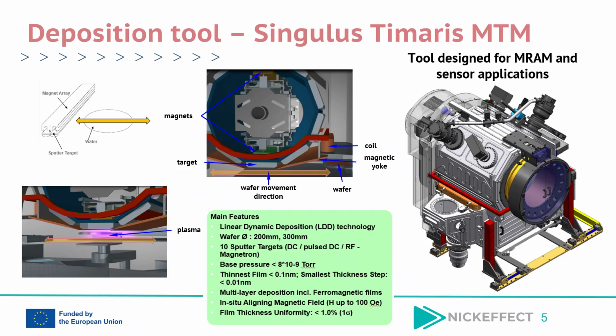Within the NICKEFFECT project, the MTJ stacks were fabricated using the Singulus Technologies MTM deposition system, which was especially developed for MRAM and magnetic sensor applications. It is based on a linear dynamic deposition technology. In this approach, the wafer moves linearly beneath a rectangular sputtering target during the deposition process.